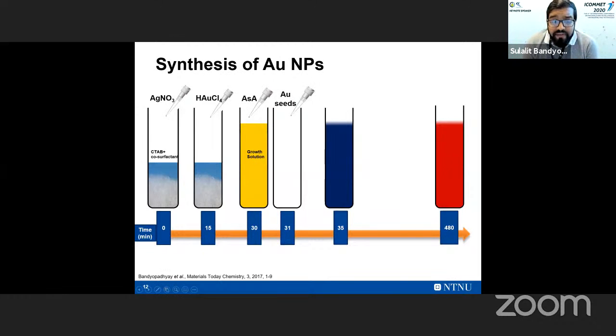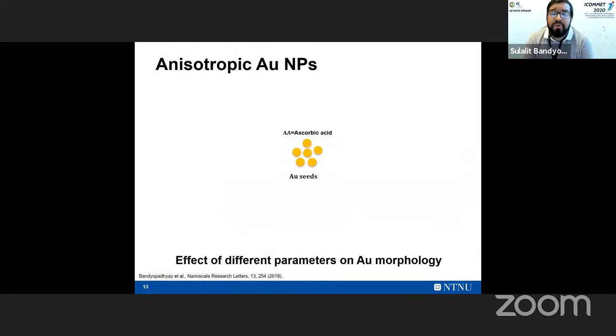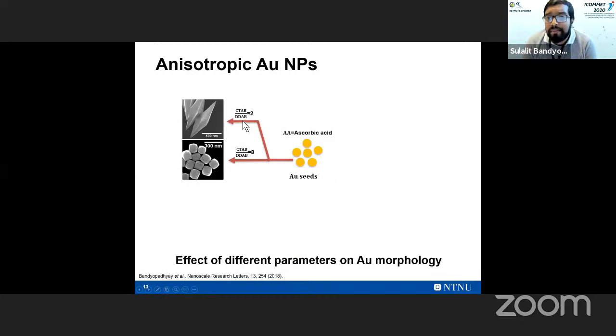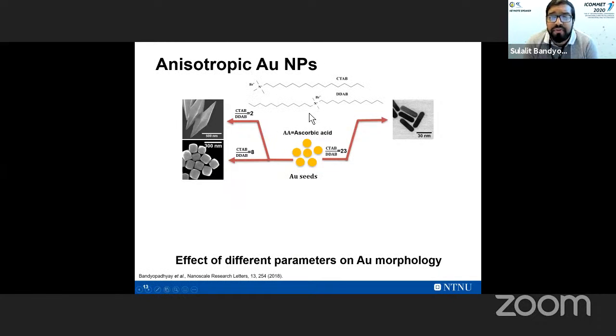Now, this method we have been working on for several years, and very recently we have looked at the effect of different surfactants or a binary surfactant. So in this slide, I'm going to quickly show you how, by varying the ratio between a single chain surfactant such as CTAB and the double chain surfactant, which is DDAB. The two surfactant structures can be seen on the top of the screen.